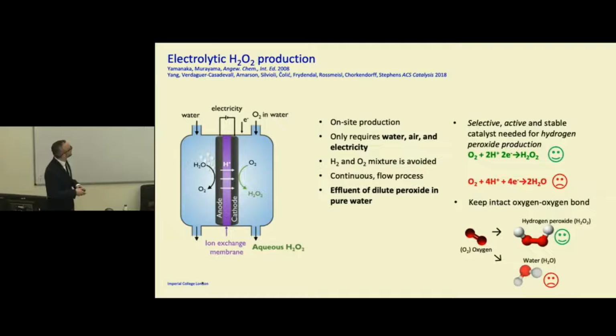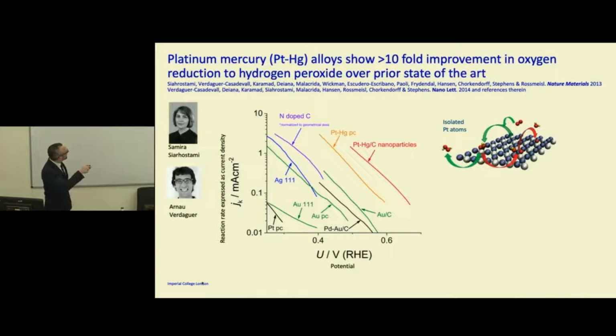What's really important is that you keep intact this oxygen-oxygen bond and don't make the more thermodynamically stable product, which is water. So we started looking at the literature, actually, and people have been able to do it, but they were not doing it particularly efficiently. So we had the idea of trying to do better. In particular, why not use a platinum-mercury alloy? With platinum-mercury you make an amalgam, so you electrodeposit mercury onto platinum, which makes a crystalline alloy at room temperature, and you have isolated platinum sites.